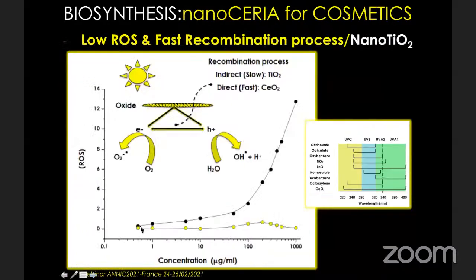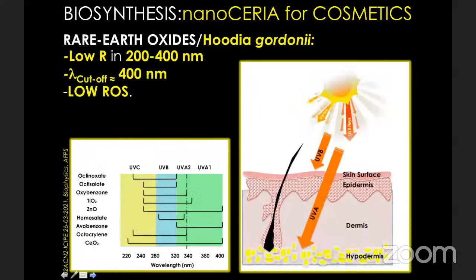Better than that, the ROS, the production of reactive oxidative species, is very low. It's close to zero relative to zinc oxide and TiO2. That means this cream made with this cerium oxide is not toxic to the skin at all, relative to other products in the market. See the efficiency of this powder. It goes through all UVA, UVB, and UVC. So it shows us how